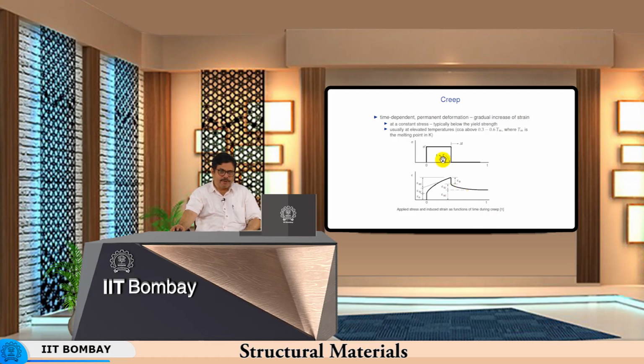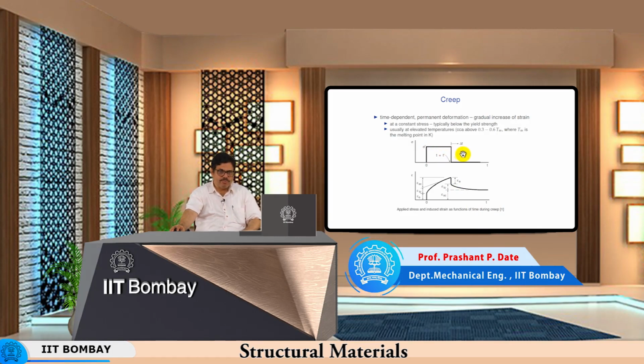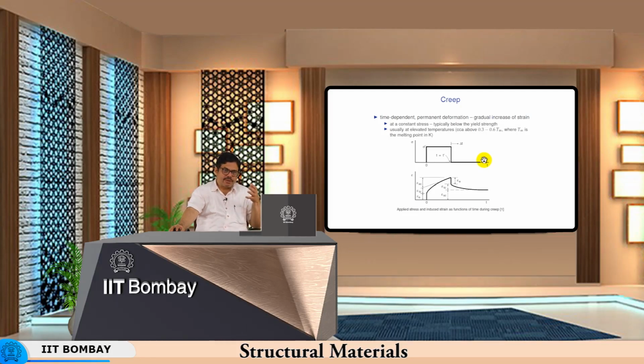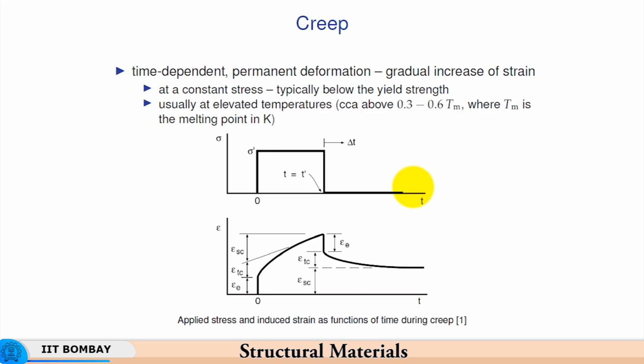We have seen that creep is basically a time, temperature and activation energy controlled process, and it happens at a constant stress, typically below the yield strength. So, there is a difference in considering the stress being maintained below the yield strength. Normally, when we design a high temperature boiler or an engine cylinder, it is subjected to a lot of internal stress as well as temperature. In spite of being below the yield strength, suppose one has used a yield limited design, let us say one has designed a boiler to consider yielding and fatigue related issues, a leak before break type of paradigm.